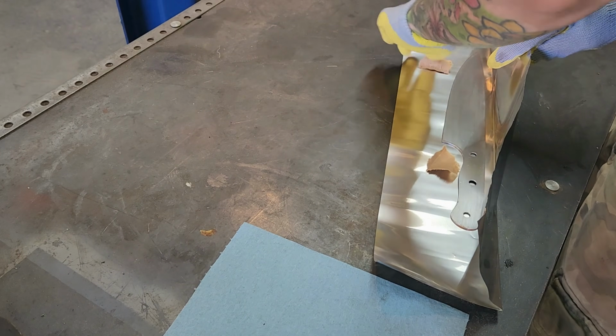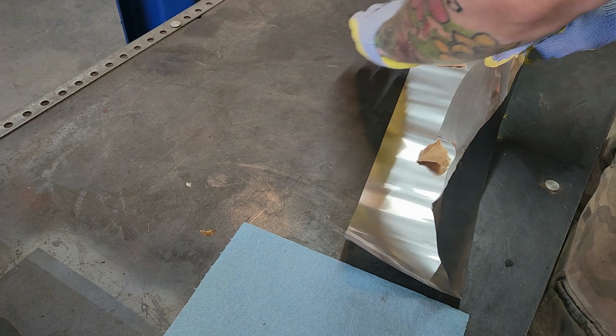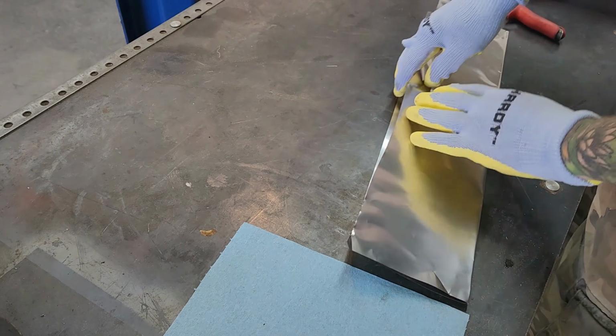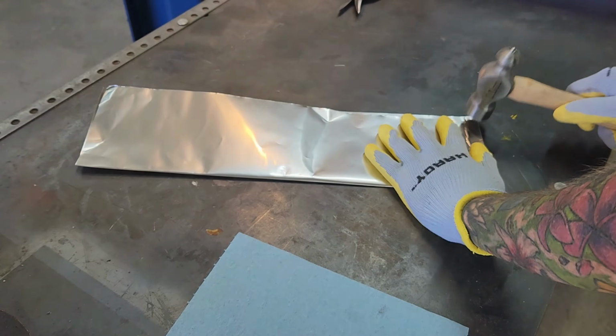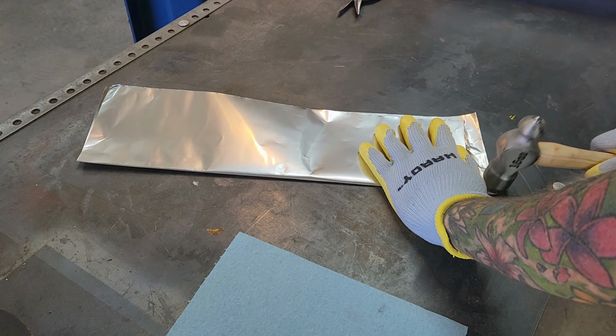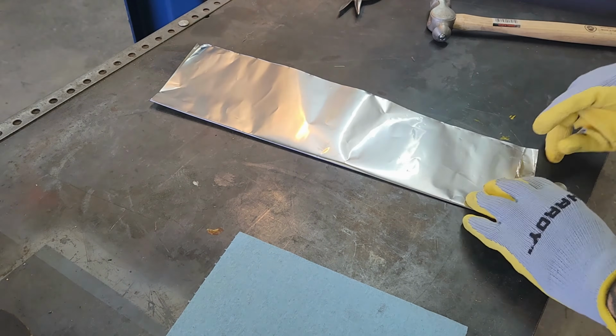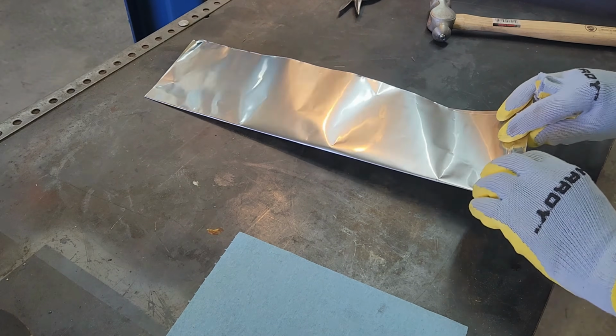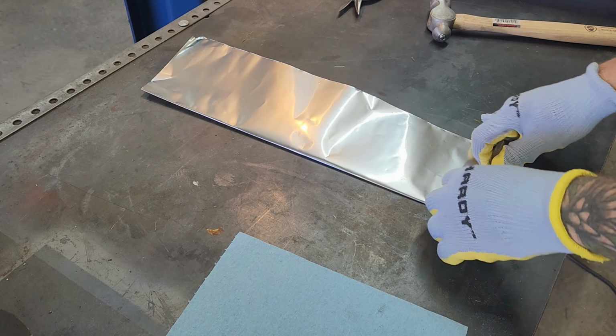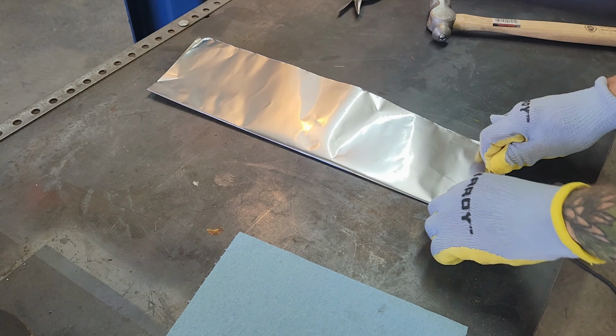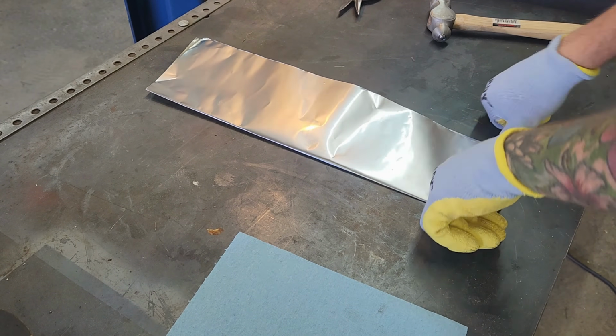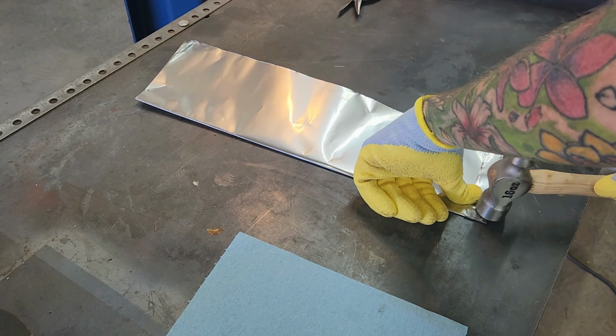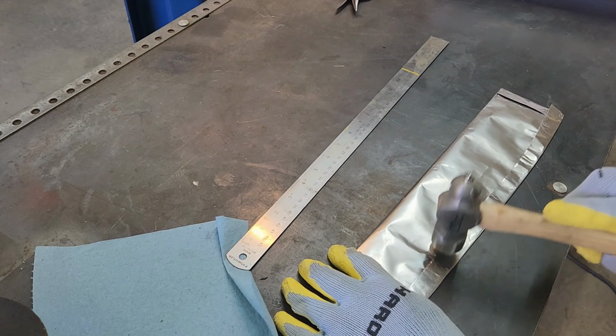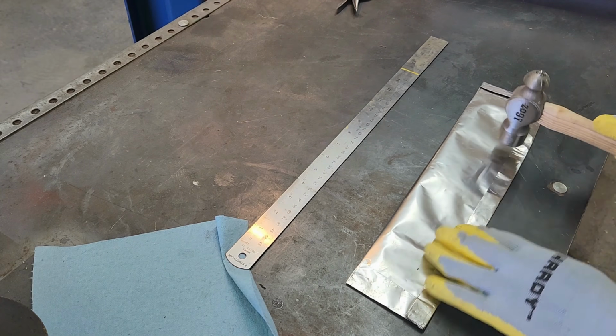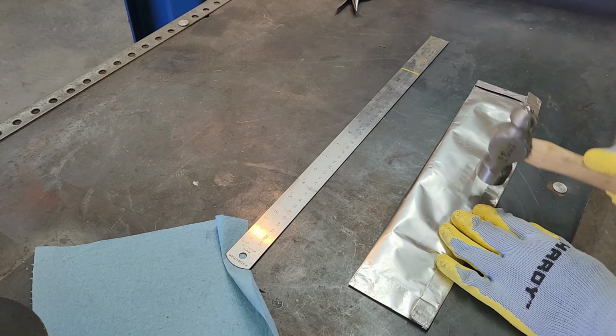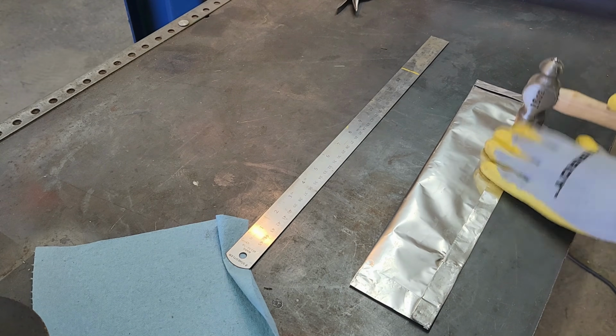Before the heat treat, I just kind of scuffed it all up, and I cleaned it with acetone after I took some sandpaper to it, just to make sure there were no residues or residual scale on there from the steel supplier. Wrapping it in foil with a couple pieces of brown paper. That paper will ignite at roughly 450 degrees Fahrenheit, and the idea is that it pulls all the excess oxygen out of the envelope, which reduces the amount of scale buildup on your blade as it heat treats.